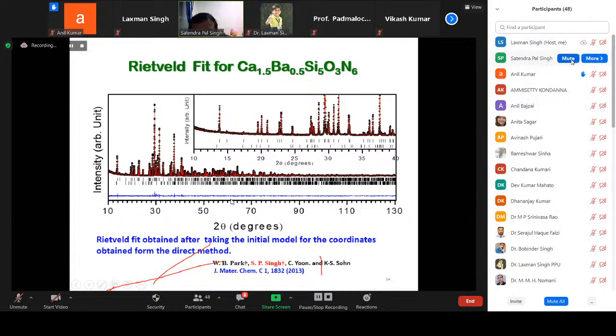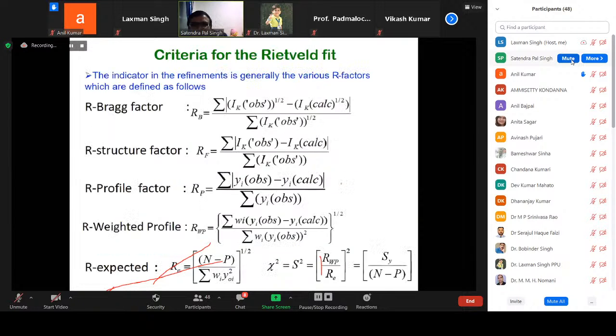So we can say that the structural determination approach is accurate, and then we also have to verify certain criteria in the Rietveld refinement. These are called the R factors, and they are called the agreement factors. We have to see several parameters, like the R Bragg factor, called RB, which is given by the intensity of the observed minus the intensity of the calculated profile over the intensity of the observed, squared. These are sums over all the diffraction spots available in the XRD pattern.